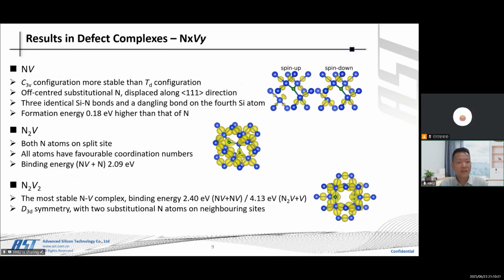The NV complex is also one of the key subjects in this research. The NV is a more stable structure compared with the tetrahedral configurations. The off-center substitutional nitrogen displaces along the 111 direction, with three identical silicon-nitrogen bonds and a dangling bond on the fourth silicon atom. The formation energy is 0.18 eV higher than that of the nitrogen.